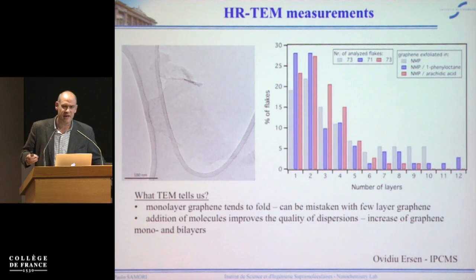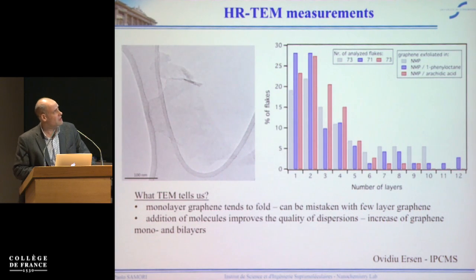Of course, you have to do your characterization. We did Raman that showed no more evidence of AB stacking of the, let's say, graphitic-like structures. That was done by Cinzia Casiraghi in Manchester. We have the high resolution electron microscopy that was done by Ovidiu, and it showed that mostly we have mono, bi, and trilayers in our sample, no matter which one of the three different types of sample we are dealing with.